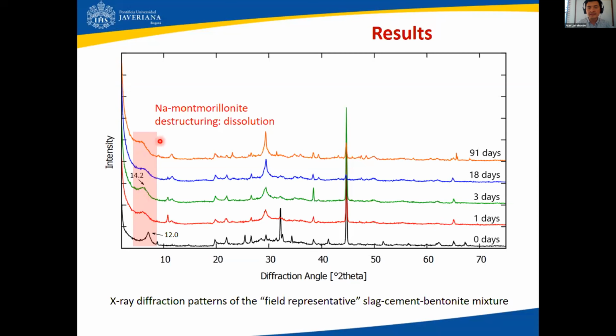So what we confirm here is clay mineral destructuring that has to do, we believe, with dissolution in the aggressive environment promoted by calcium hydroxide and exothermic environment during cement hydration mainly. So what you can see here also is that beyond perhaps the 18th day, you can argue that you no longer have really montmorillonite. The slight shift in the peak may have to do, or actually we believe it has to do, with cation exchange that is taking place because at that pH, the particular calcium oxide or calcium hydroxide form tends to replace or transiently replace the sodium by the calcium in this structure.